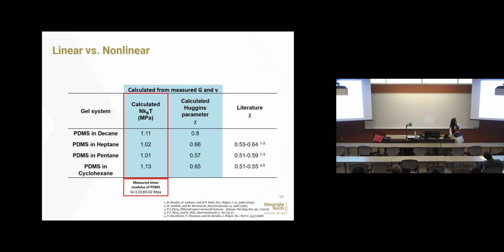N times kT is actually the shear modulus of dry PDMS before it swells in any organic solvent. And we can do an independent measurement to compare with our calculated value. It compares very well. What is interesting is about chi. Chi is a chemical parameter. For the PDMS system, in the literature, people have used many different chemical ways to measure this chi. And our mechanically characterized chi value is very close to the literature-reported value.